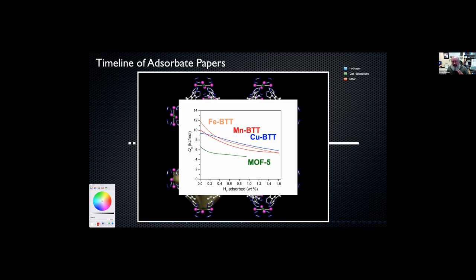So in the back of our minds, this was all, you know, how do we characterize materials that have high delta H's, and how do we improve the material synthesis to get towards a room temperature hydrogen storage material? And in principle, the theoretical value is somewhere between 15 and 25 kilojoules per mole. And you can see that we're a long way away from that at the beginning of this research.